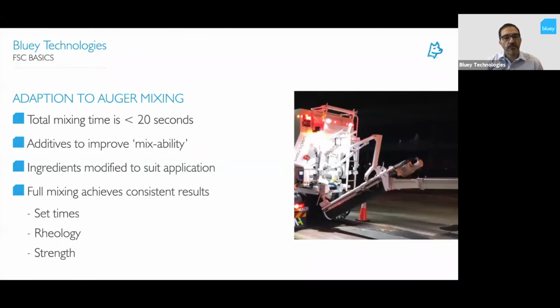Besides the trucks being advanced, we've also had material advancements, as I've touched on already. So the total mixing time now is less than 20 seconds with these trucks, as opposed to with an agitator truck, which might have been mixing for even up to 20 or 30 minutes before the concrete was poured, or where you're using a grout mixer where you had 3, 4, 5 minutes of mixing time before you had to apply it.